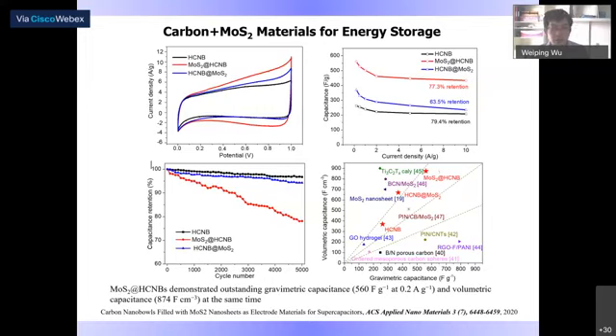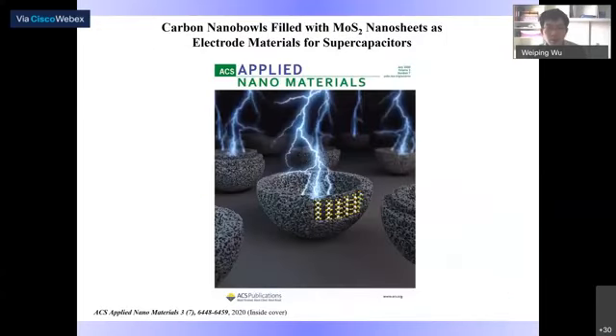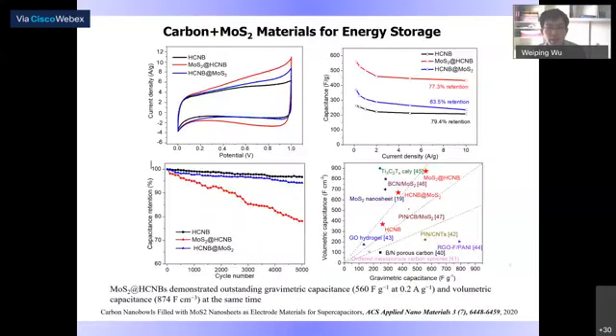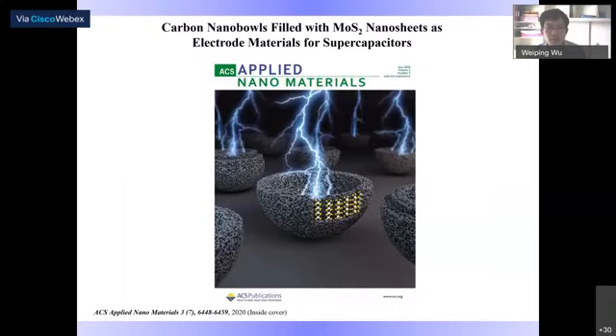And besides this, the cycling stability is still very impressive. The degradation is quite small, less than 5%. So this paper has been published as the inside cover of ACS Applied Nanomaterials.